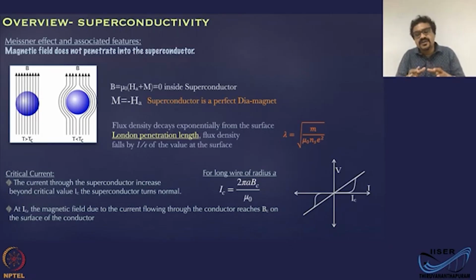Running a current through a superconductor is like applying a magnetic field. When the current is high, the field also will be high, and at IC, at critical current, the field will be the critical field. So typically, this is a cartoon of the critical IV, current-voltage characteristics, where there will not be any voltage developed until the critical current is reached. Suddenly there will be a resistance, and there will be a voltage developed, and the resistance will be equal to the normal state resistance of the material.